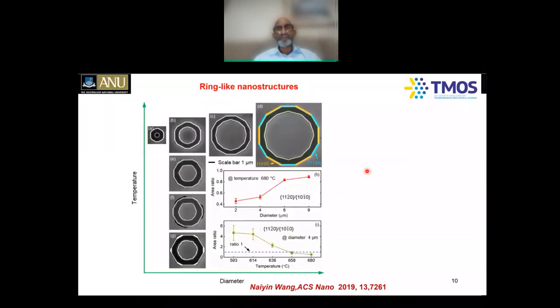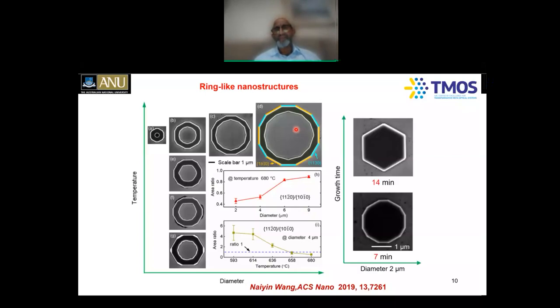You can see that you open a ring. Again, you can see these alternating facets, and you can get a beautiful ring-like structure. And again, Naiyin Wang has spent a lot of time optimizing growth conditions. I will not have time to go into the details of that. If you keep growing further, this gap in the middle gets filled up, and you end up finishing these horizontal membranes, which are really hexagonally faceted again here. So again, these could be useful for MEMS applications or membrane lasers and other things. We've also been using these rings as ring resonator lasers, which I will come back to and share with you.